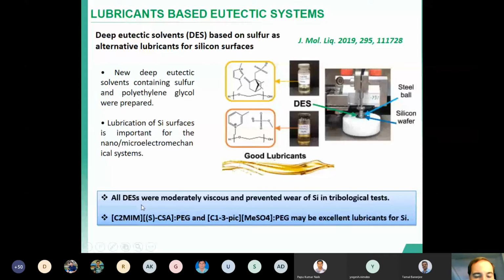All deep eutectic solvents are moderately viscous and prevent wear of silicon in tribological tests, and the best ones are these two mentioned here: an imidazolium salt with camphor sulfonic acid, in combination with polyethylene glycol, and a picolinium, methylpyridinium, with methyl sulfate anion with PEG. They are excellent lubricants for silicon, and it's possible to use them pure. And this is something that we are now exploring, other eutectic systems, some natural eutectic systems, hydrophobic eutectic systems, to see if they are interesting for application as lubricants.